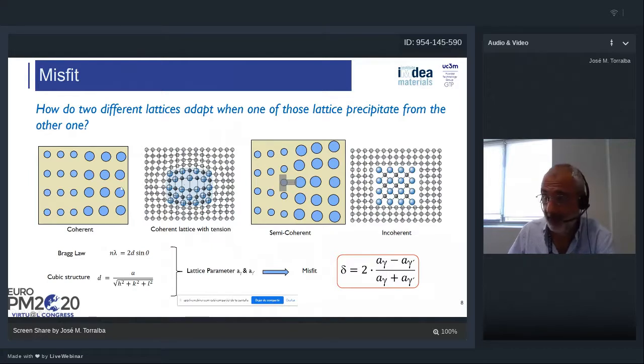Here we have different levels of coherency. Here we have two phases completely coherent. Here we have a coherent lattice with some tension. This is coherency, but with very different size of the atoms. In that case, we have some tension in the lattice. Also, we can have semi-coherent materials. Here we have this semi-coherency in this direction, but not in this one. For this reason, we mention it as semi-coherent, and we have a completely incoherent material. In that case, we will have a higher lattice incoherence and a higher misfit.